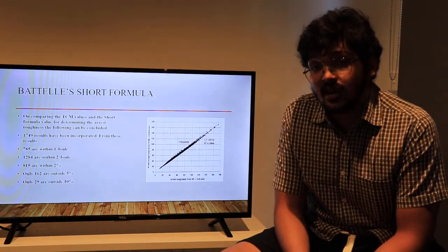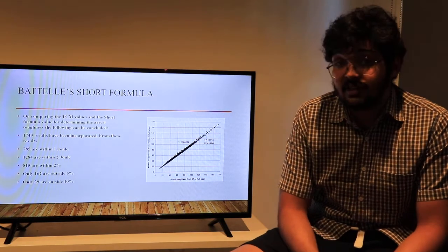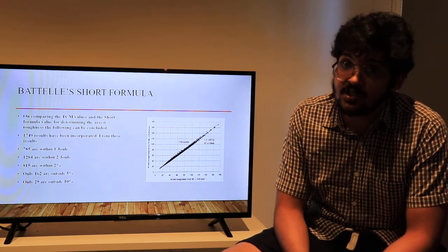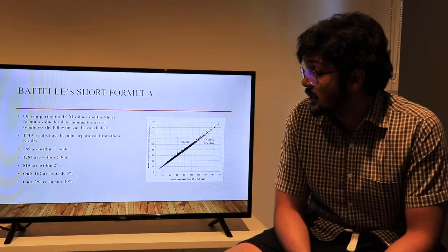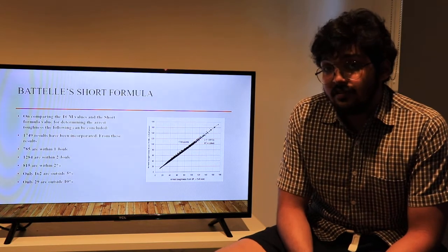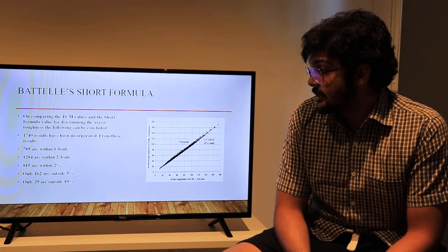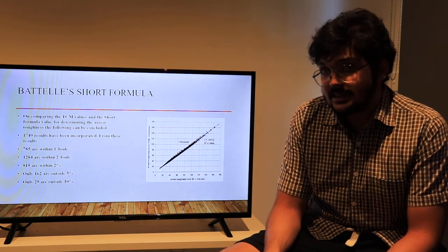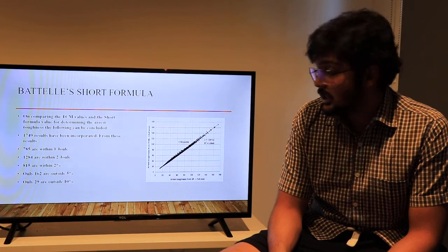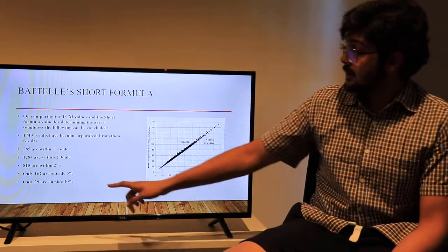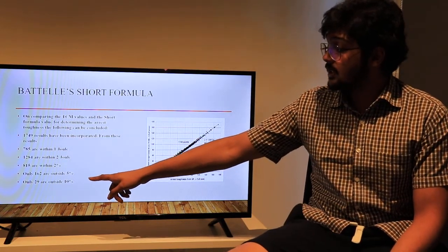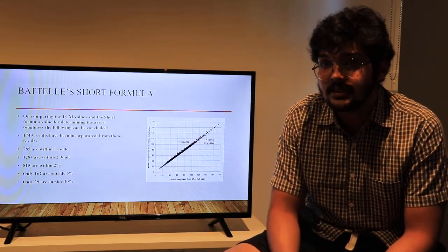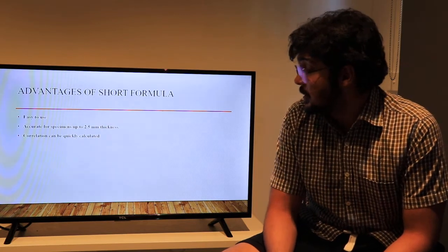Out of these 1749 results, 785 are within a difference of 1 joule of arrest toughness, 1284 results are within 2 joules of toughness, 815 are within 2% difference, only 162 results are outside 5%, and only 29 results are outside 10%. Now, the 29 results which are outside 10% difference are for specimens that are less than 2.5 millimeters.